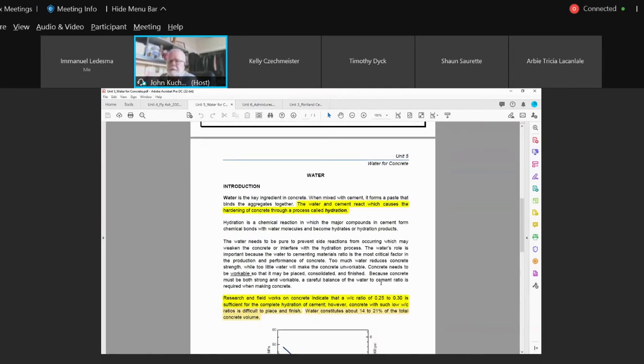What water do you use for mixing? If you can drink it and you don't die from it, it's good for concrete. So in other words, potable water, the water that comes right out of your tap, that's ideal. You know it's going to be okay because it's been tested, and all the ingredients that have been determined from a chemical analysis of the water are not detrimental to concrete, as long as those levels are within a certain range. But typically, potable water is the ideal water for mixing concrete.